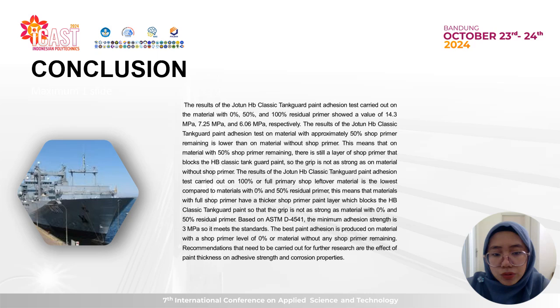The result of the Jotun HB Classic Tankguard paint adhesion test carried out on material with 100% or full shop primer leftover is the lowest compared to material with 0% and 50% residual primer. This means that material with full shop primer has a thicker shop primer paint layer which blocks the HB Classic Tankguard paint, so the grip is not as strong as on material with 0% and 50% residual primer. And based on the standard, the minimum adhesion strength is 3 MPa, so it meets the standard.